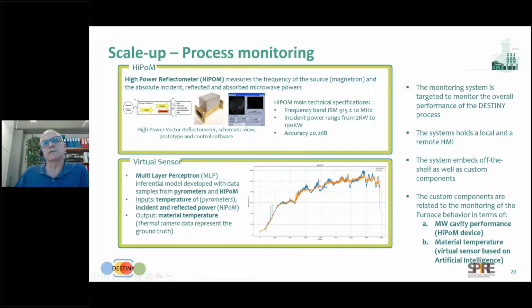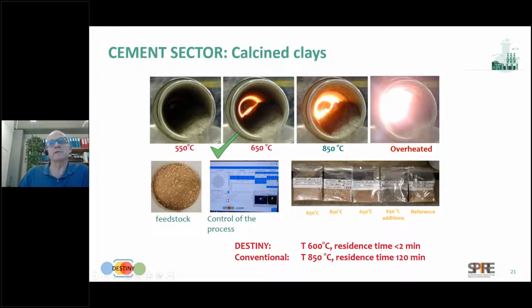The real temperature is the blue one, for example, and the brown one is the simulation you can obtain with the soft sensor that a team is developing. So, some examples. In the cement sector, with calcined clays, we obtained around 600 degrees, a perfect target and perfect results. More than that was useless, not needed.